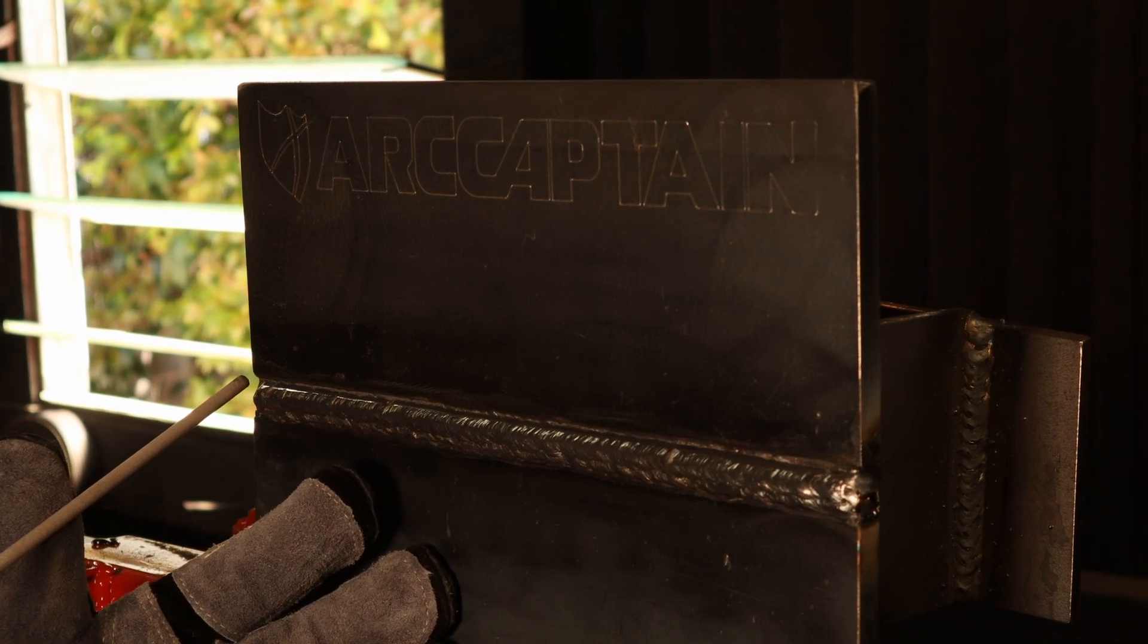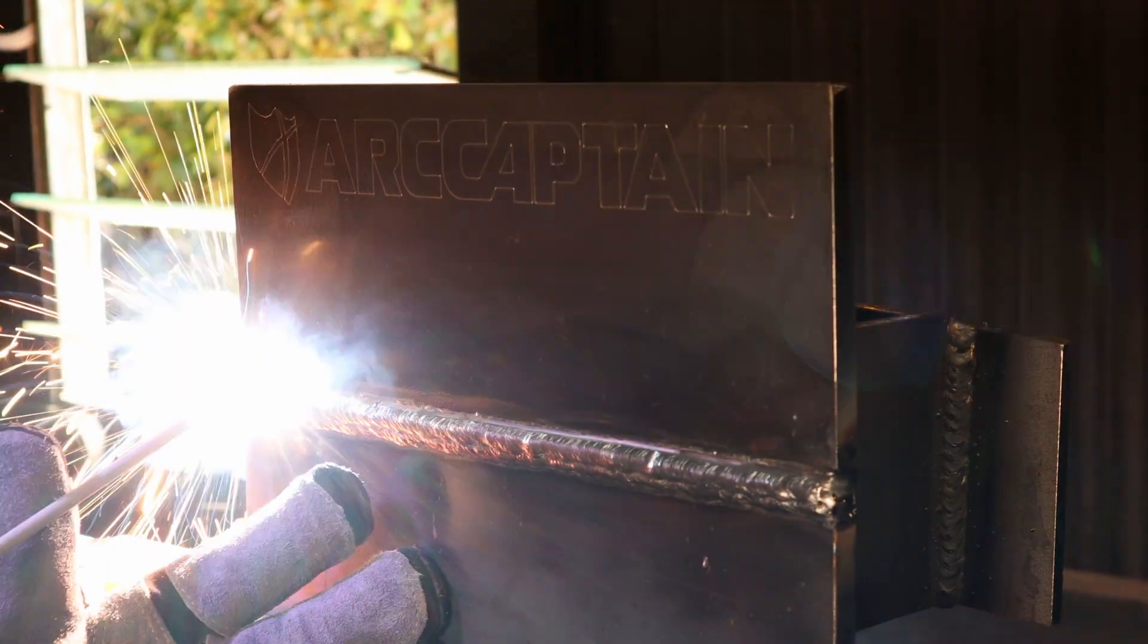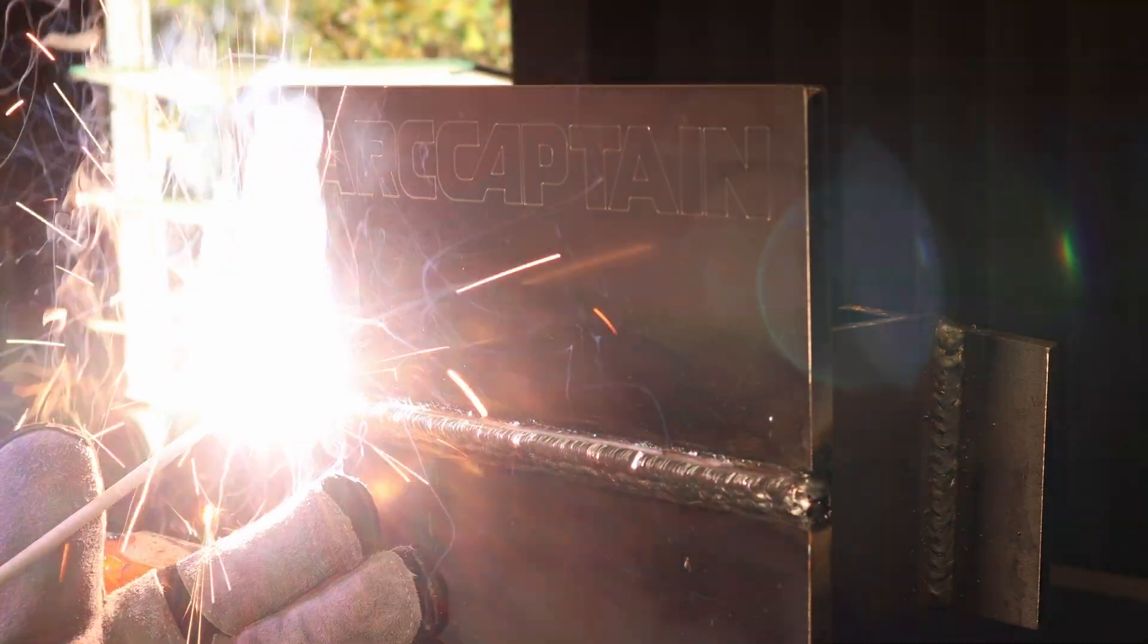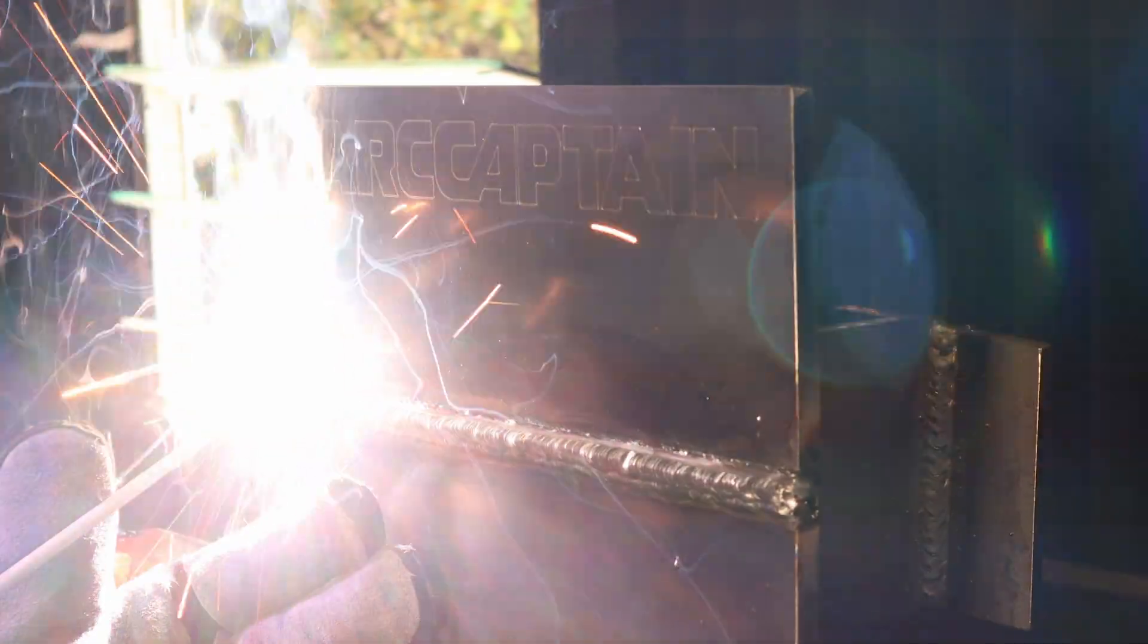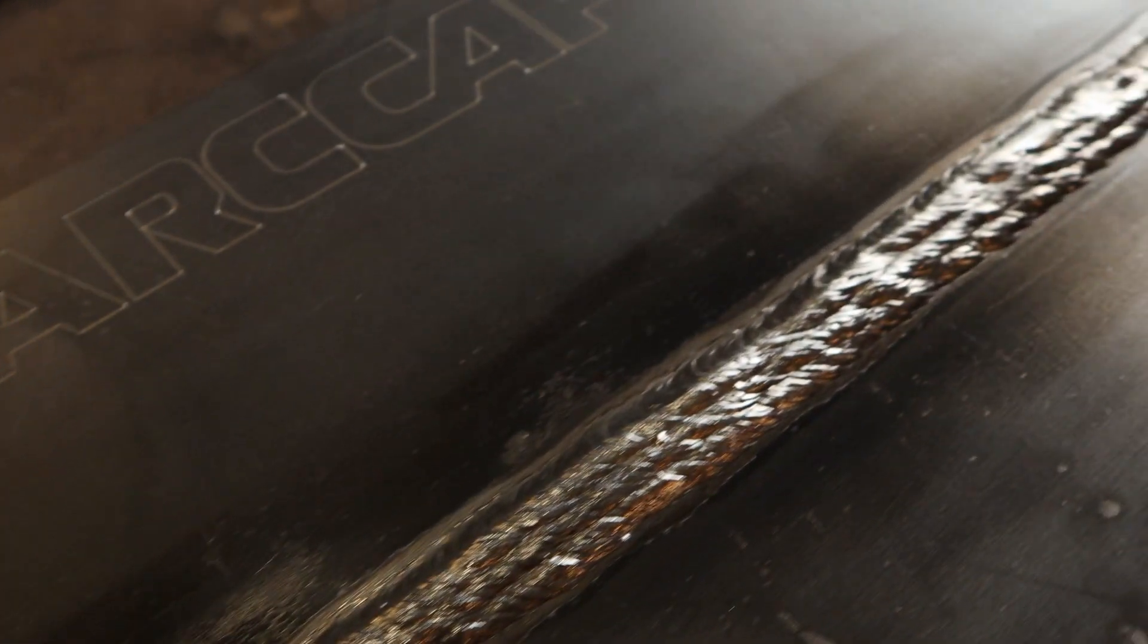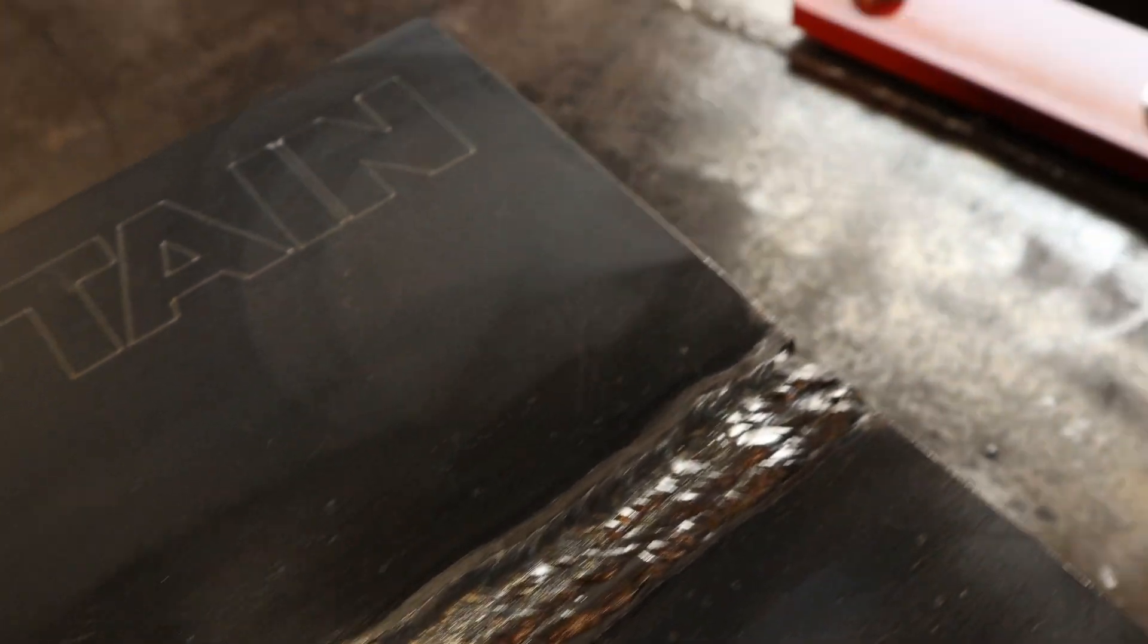I am angled down slightly to prevent any overroll. The bottom of the weld pool should just cover the plate for a nice profile that I can lay the next two beads over. If you are going to do a lot of stick welding with your multi-process welder, having arc force and adjustable hot start functions makes fine-tuning the welder for each rod or position a lot easier.